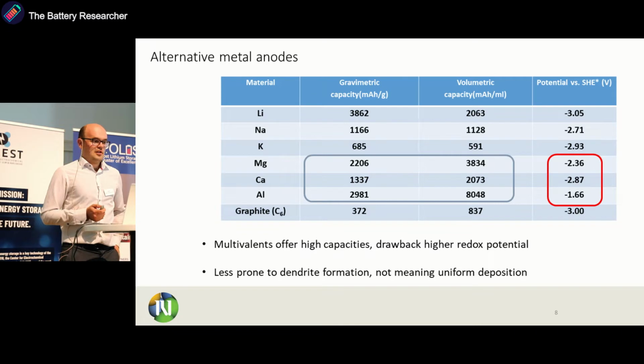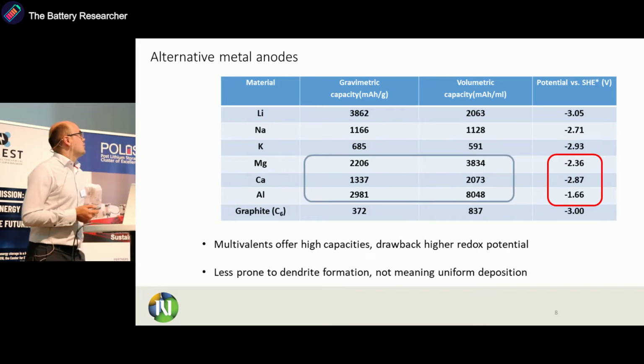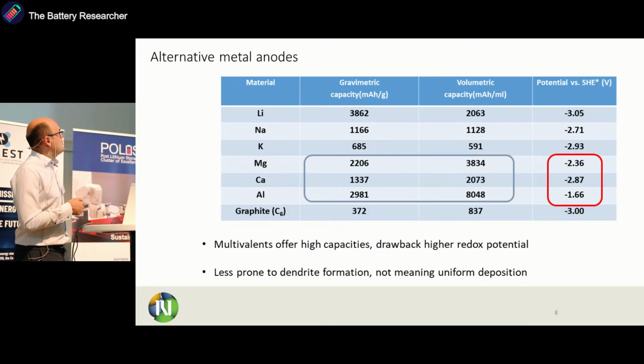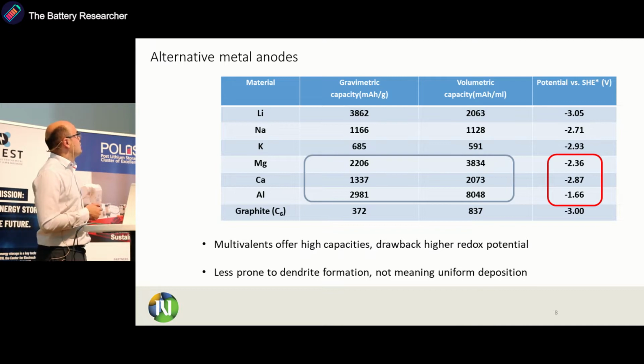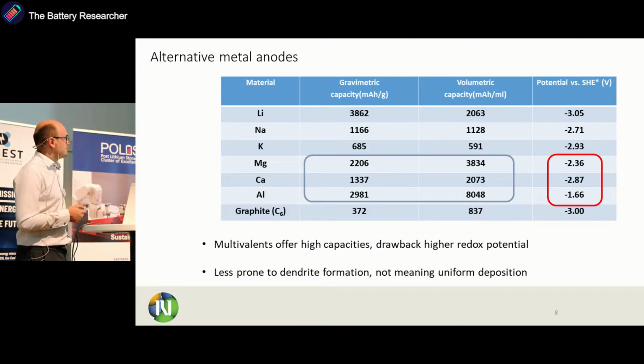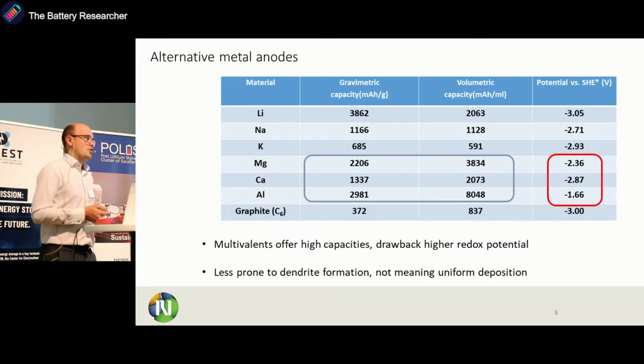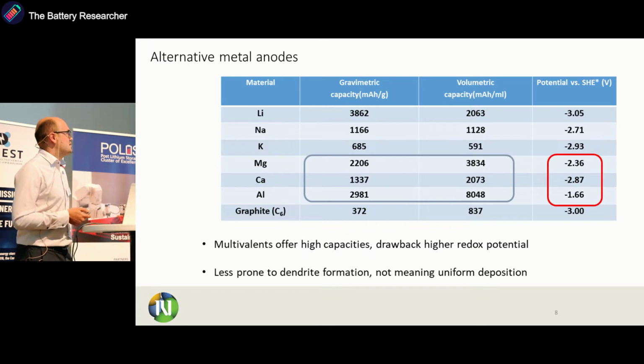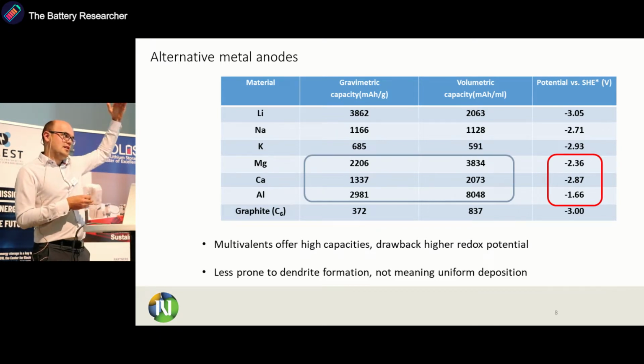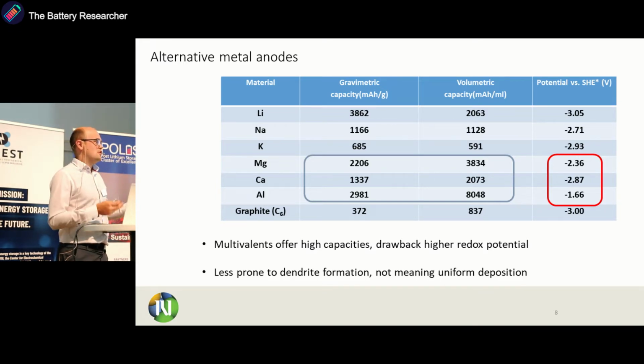There are also a lot of challenges in application, and mainly these are connected with the fact that when we have passive layers in multivalent electrolytes, they typically do not conduct ions. And this formation of passive layers is strongly connected with their redox potential. Because we know that calcium is really close to lithium. It basically always decomposes the solvent and salts and forms a passive layer. While in the case of magnesium and aluminum, the redox potential is slightly higher, and when we have suitable solvents and salts, we do not form a passive layer.